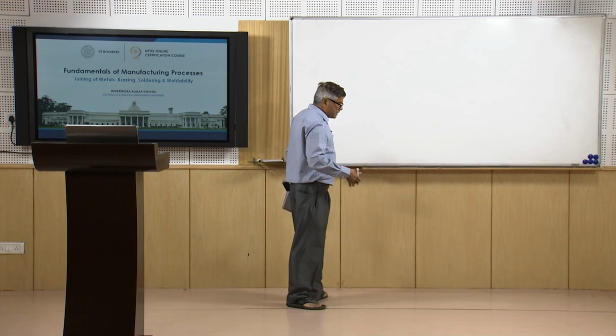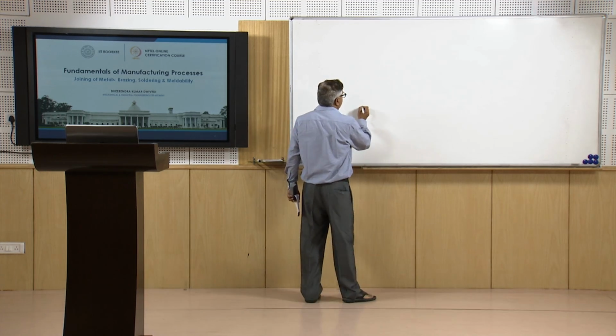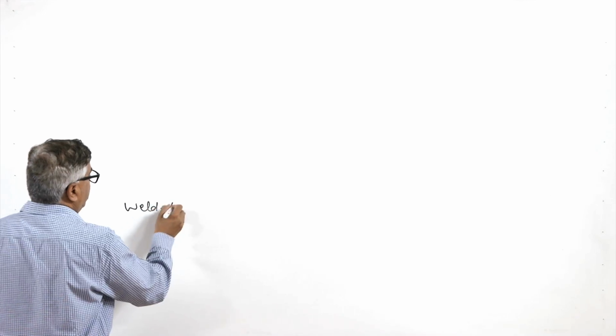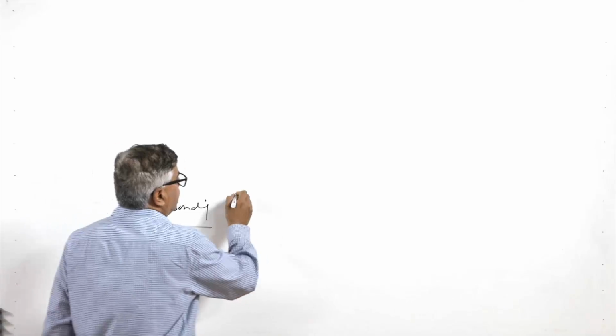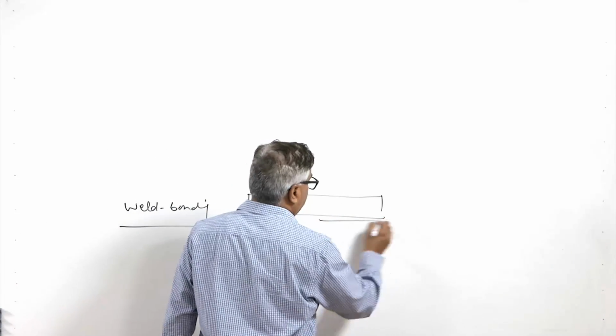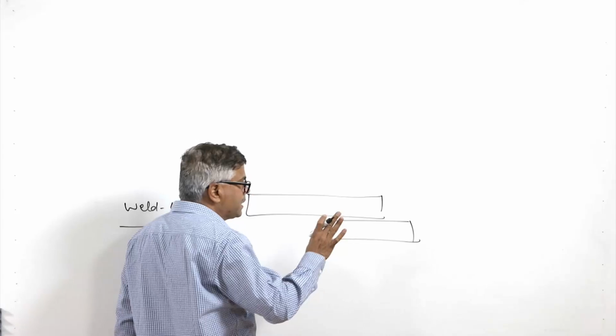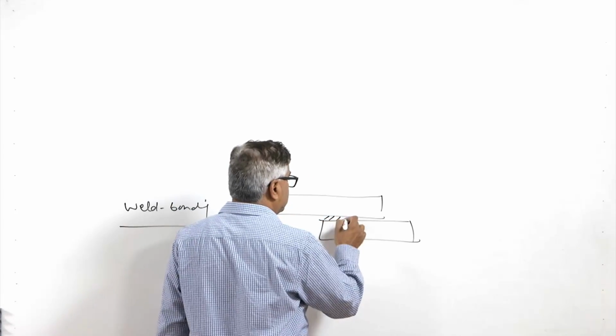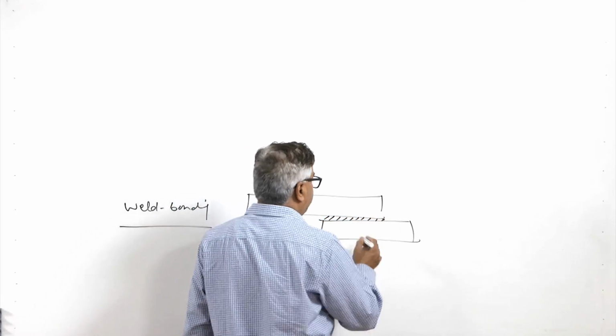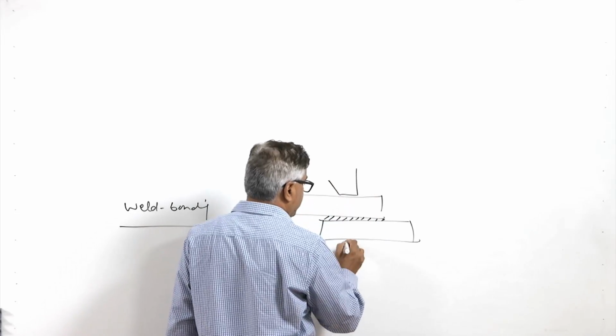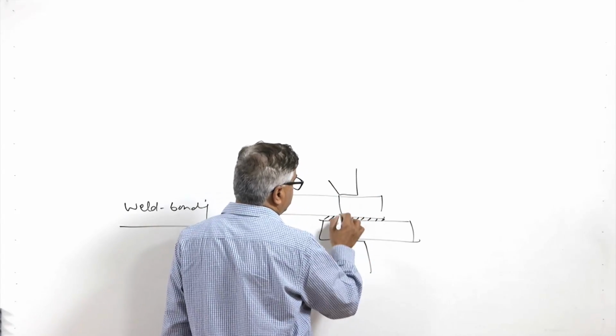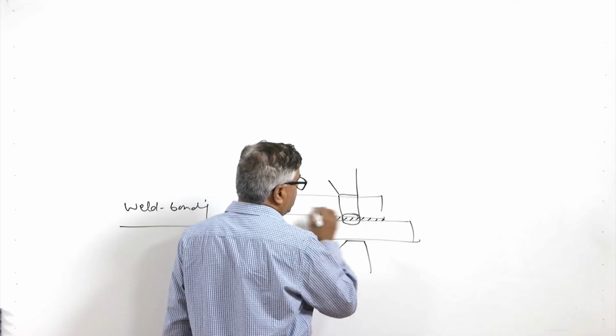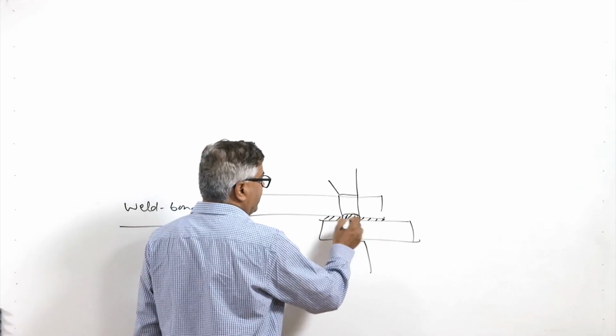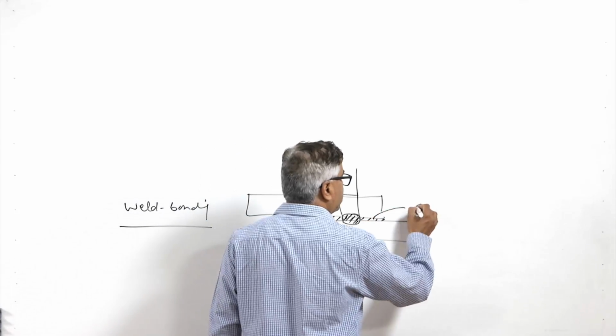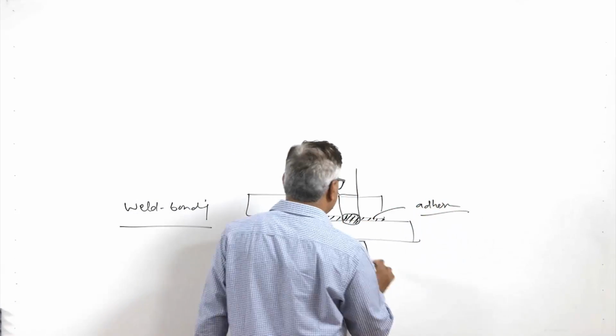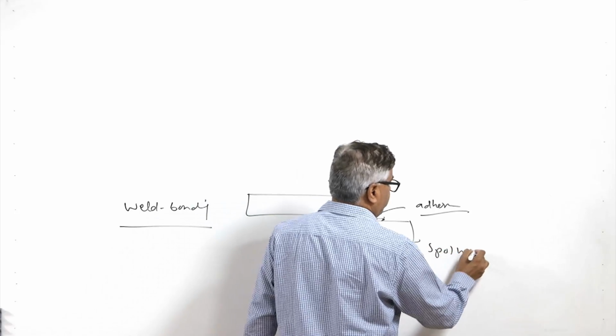In order to increase the strength of the adhesive joints further, another combination like weld bonding has been attempted, wherein the plates to be joined are kept in overlapping position. So, here the two methods are used. Either first the adhesive is applied, and then the spot weld is made. So, wherever there is adhesive, due to the flow of current, the adhesive in that area is burned out, and a metallic weld nugget is produced. So, it combines the effect of the adhesive joining and the spot welding.